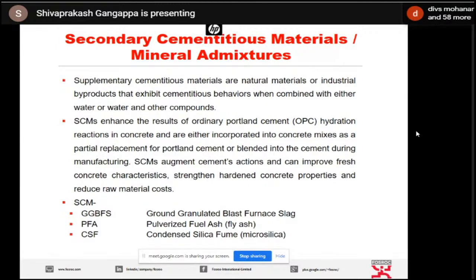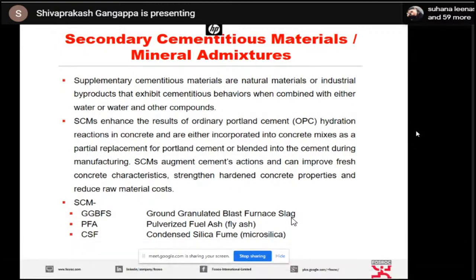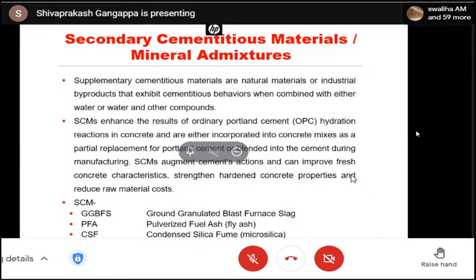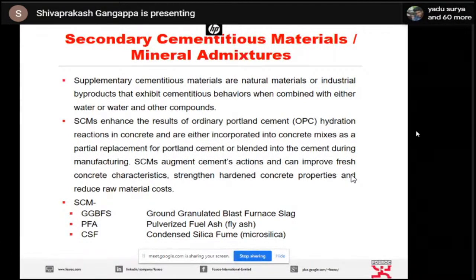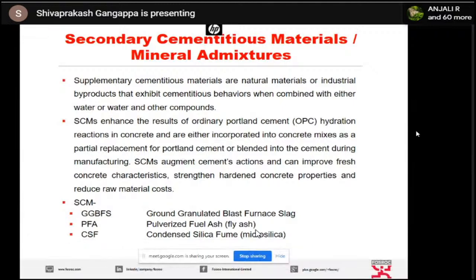In case of a high performance concrete, it is not going to replace OPC. OPC we will maintain up to 450. Anything beyond this, because there is no codal provision or codal restriction, you can replace the fine aggregate with the secondary cementitious material. There are possibilities of doing this also. So such kinds of restrictions are not there in the code in the mix design. So we go with 450 kg of OPC, which is very badly needed for hydration of cement. Then we also go for a replacement of fine aggregate using GGBFS or fly ash. So this is one way of operating mix design as a high performance concrete. Thereby it also meets the requirement of IS 456 or IS 10262. Otherwise, this concrete cannot be used. This becomes part of a research kind of job which practically cannot be used.